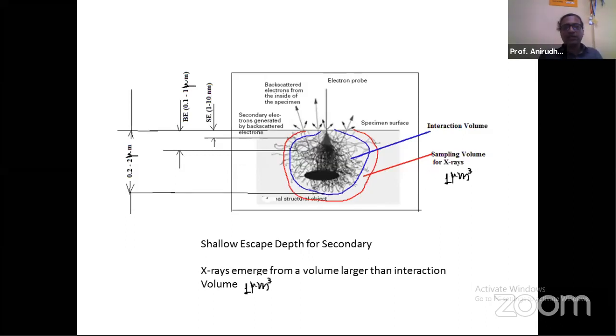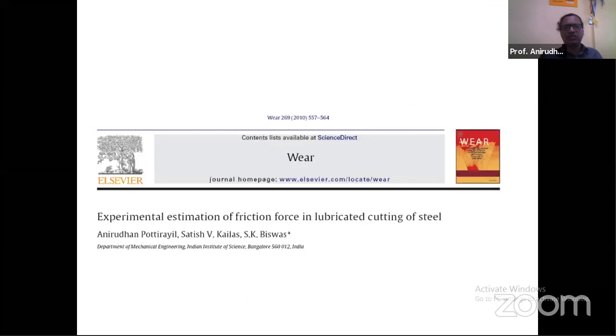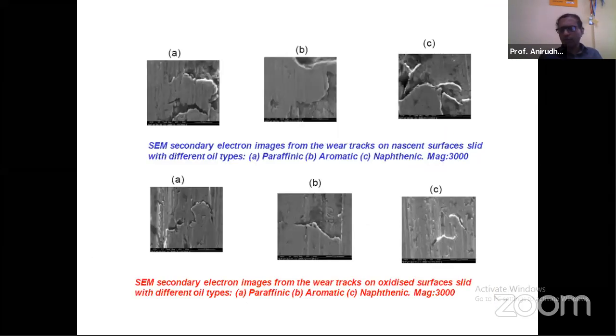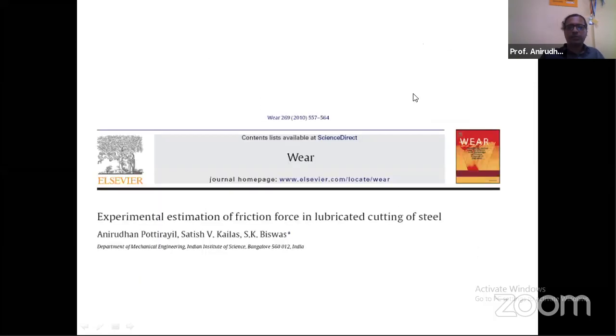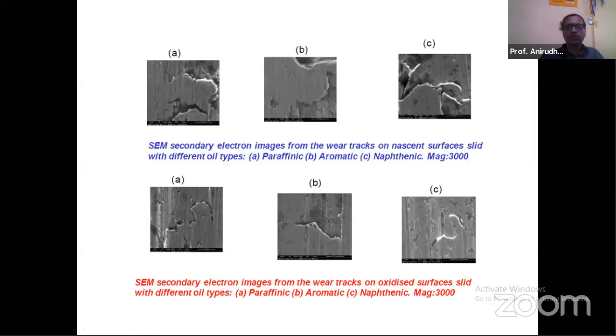So this is about SEM. I'm not going into the details of this. I'm going to show you SEM images from experiments which are published in another source, which show these top figures are where we got a very large amount of friction, whereas those bottom SEM images are those cases where we got slightly lower values of friction.